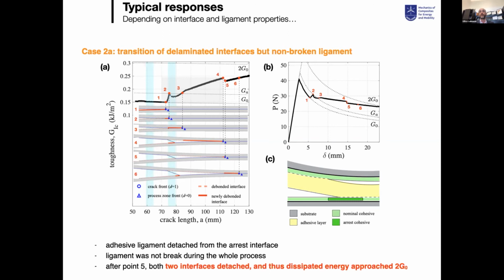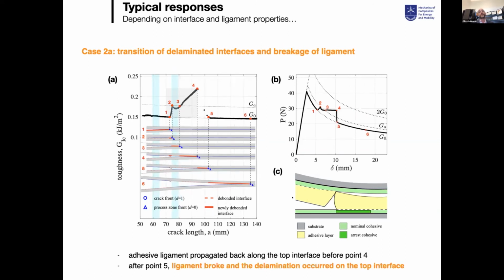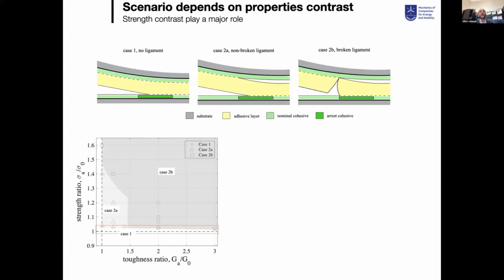and you have a third mode of failure. That is a situation where you start to initiate the ligament, you start to have a local reinforcement, a local increase of the toughness. This is the toughness as a function of the crack extension. So toughness is increasing, and then you break your ligament and you come back to the initial properties. So what you want to do to be able to design something like this is really to play between these three schemes of degradations and to be able to control this one. That means to be able to control the development of ligaments that are going to get a tougher joint to increase the property of your joint.